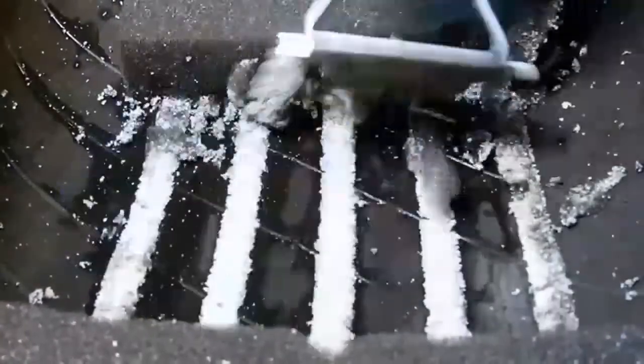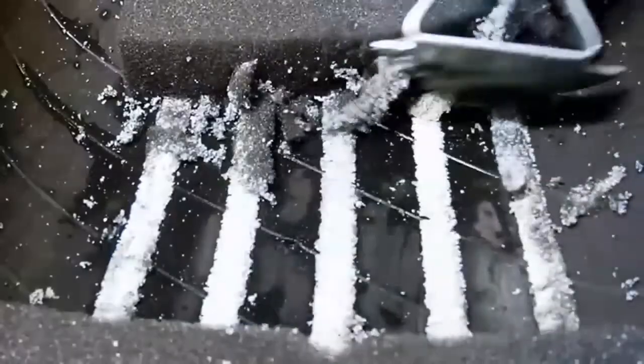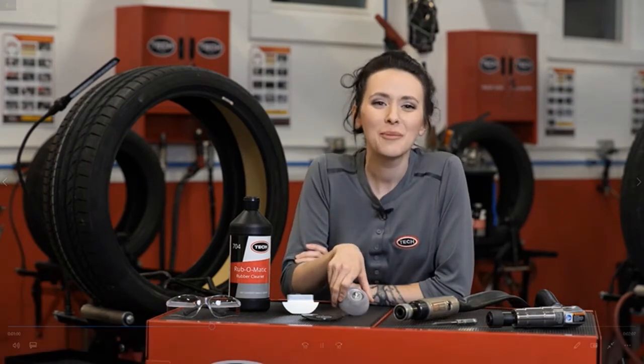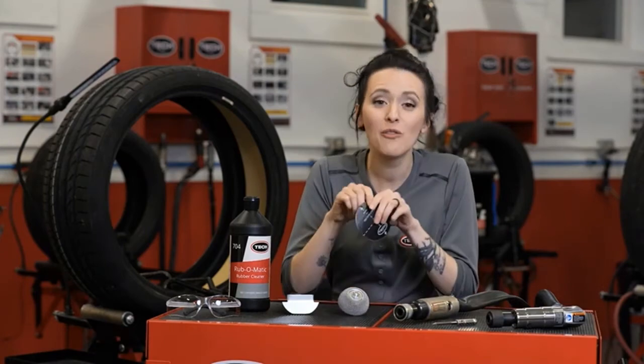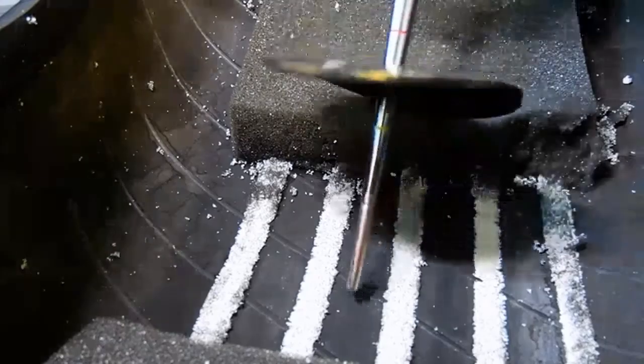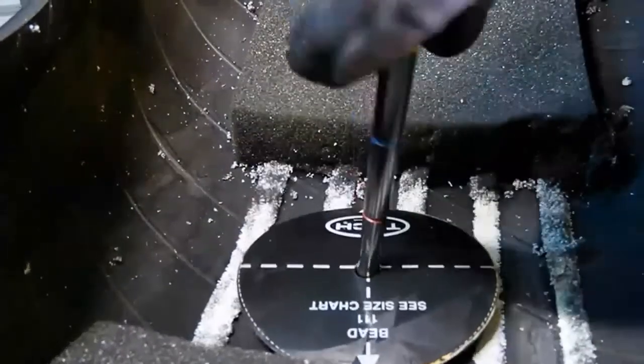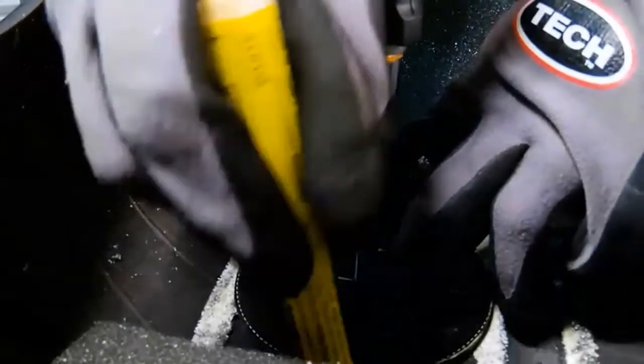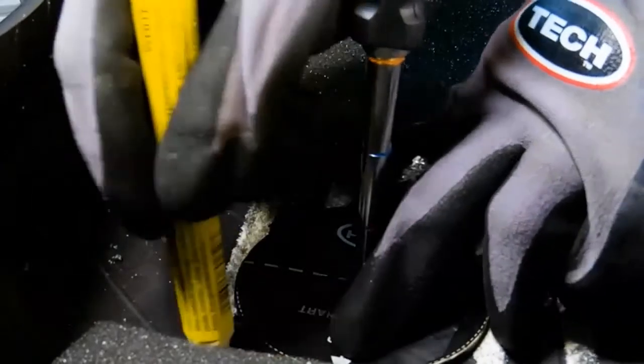This tire has a cured adhesive, so we will proceed with cleaning the inner liner. Spray or pour Tech Rub-O-Matic on the area to be cleaned. And while the area is still moist, use a rubber scraper to remove any contaminating substances. This process should be repeated 3 times to guarantee complete removal of contaminants such as silicone mold lubricants used in the tire's manufacturing process. Failure to remove these materials can lead to contamination of the repair area and possible repair unit failure. It will also help prolong the life of your buffing wheel by preventing buildup on the tool.